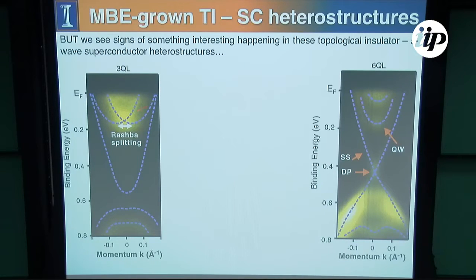Here we see 2 different samples, and so this is for a 3 quintuple layer system, and the gap that we see here is the hybridization gap. And for the 6 quintuple layer system, of course, it's sufficient enough where the penetration of the surface states into the topological insulator are sufficiently decayed where we don't have any hybridization gap, and since time reversal symmetry is still obeyed in this system, even though we've coupled it with a superconductor, we still expect to see the Dirac point.